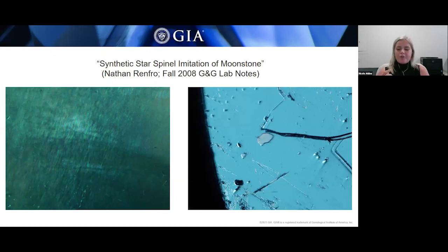In the photomicrograph on the right, you can see that it's actually displaying a blue metallic coating that was on the back of the cabochon, and it was added to create that adularescence seen in moonstone. And I believe this is still the only laboratory-grown star spinel seen by this contributor, as well as one that's imitating moonstone.